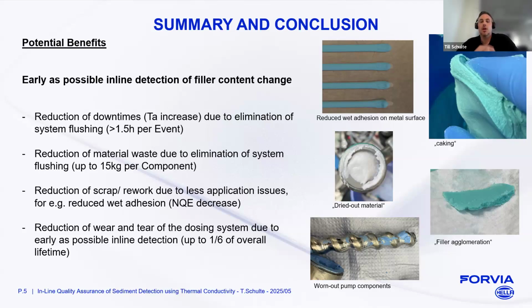Normally we could only see it, as in the left upper picture, that a higher filler content leads, for example, to a reduced wet adhesion on a metal surface. In this case, for sure, you could detect the filler change, but then the material is already processed, and this means the complete system, from the preparation system to the dosing head, is full of not good material, or material with a higher filler content. Sometimes it's as well already produced, and this means you have to flush the complete system, which normally needs around 1.5 hours per event.